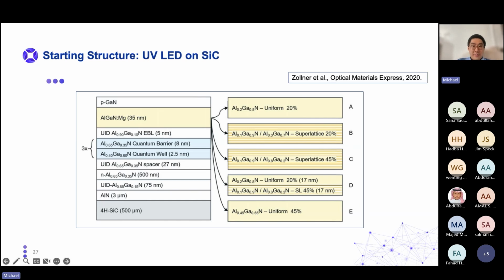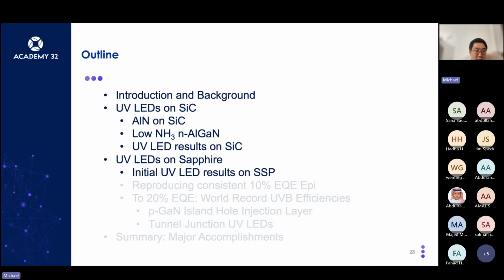Because aluminum gallium nitride, even with short period superlattices to enhance the hole concentration through polarization effects, or through graded layers or polarization doping, is still not providing nearly enough holes for this device to operate well. So we typically have a layer of p-type gallium nitride on top of a p-type aluminum gallium nitride, and this supplies all the holes that are needed for the device. So the initial UV LED results on SSP, single side polished sapphire, aluminum nitride templates.